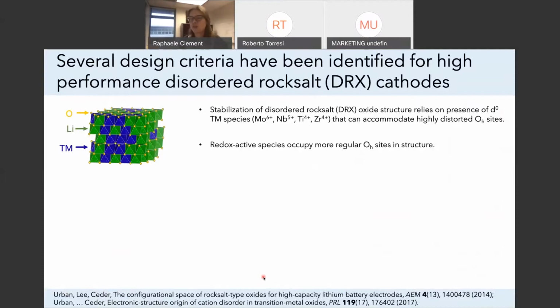So over the last 5 years, as people have learned more and more about disordered rocksalt compounds, a few design criteria have emerged. One of them is that in order to stabilize a cation disordered structure, such as this one, where now you no longer have a transition metal layer and a separate lithium layer, you need to introduce transition metal species that can accommodate highly distorted octahedral sites. And the reason for this is that now that you don't have these layers, the octahedral sites in all of these layers will be slightly distorted.